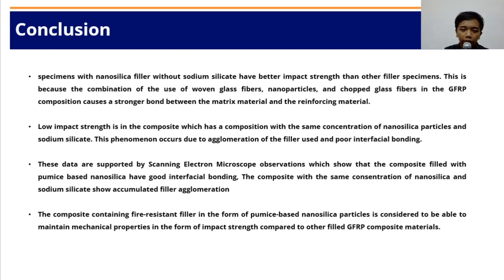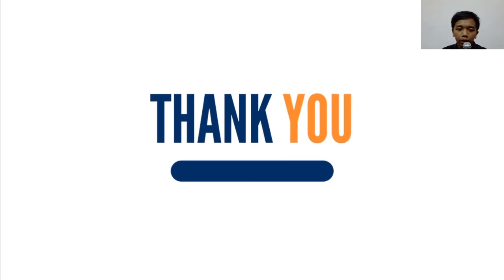From the results that have been obtained, the composite containing flame retardant filler in the form of nanofiller pumice particles was considered able to maintain mechanical properties in the form of impact strength compared to the other filled GFRP composite materials. Well, ladies and gentlemen, that's what we can share with you about the result of our study about the effect of pumice-based nanosilica and sodium silicate addition on impact strength of GFRP composite. I hope this research can be useful for us.